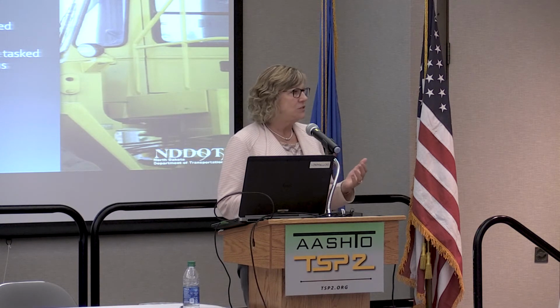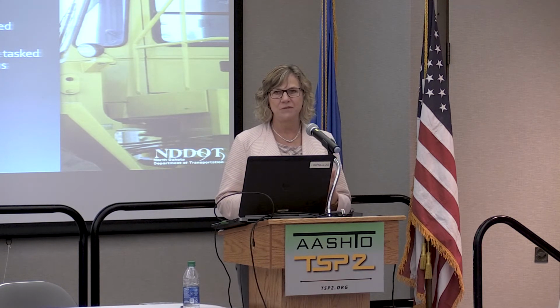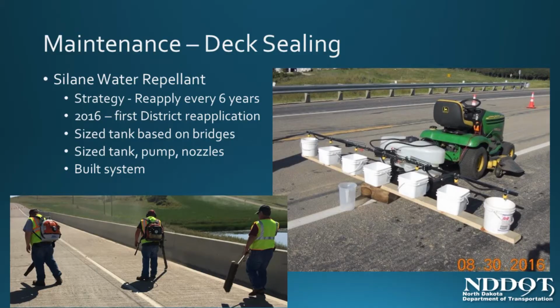We try and get them to do as much as we can. We'd rather not contract things if we don't have to, so we kind of task them with getting a lot of things done. They also, when they're not doing all of these things, provide some maintenance activities. We do deck sealing. As I mentioned, during construction, we do it right away. We have in our bridge maintenance manual that the silane needs to be reapplied every 6 years. It really wasn't happening before.